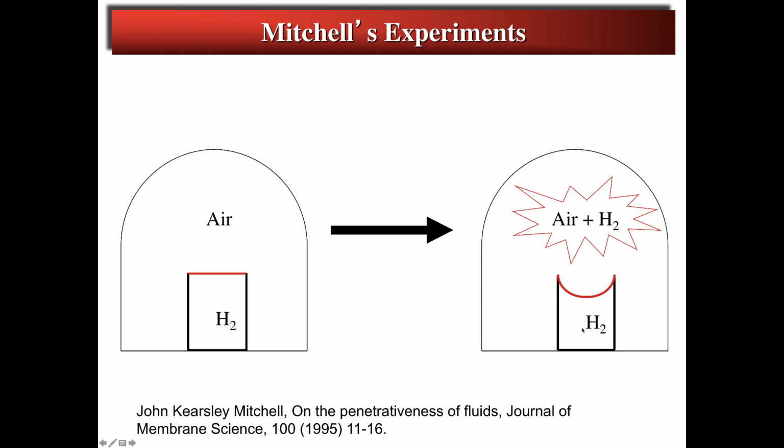And so he was surprised that the hydrogen could penetrate its way through the membrane to get out into the air when there's no pressure difference applied. And he said it must be by some inherent power of considerable amount. And he found that the facility of permeation was much greater for hydrogen than for atmospheric air, because he found almost no air inside this bottle. And so hydrogen is just way more permeable through this natural rubber membrane than air gases are.